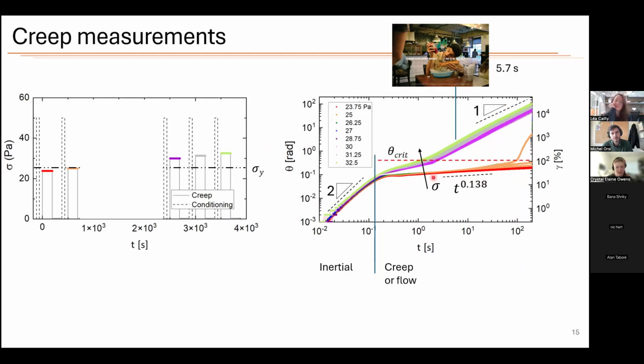And then we can see there also seems to be a little bit of a transition region here, so we can mark a critical rotation angle. Right, so this is tracking what is the angle of rotation as you apply the constant stress. And this is a function of time. So we have the angle here, and then we have the strain here. I mark both of those because the angle is something that we know for certain. We know where the vane is, we know how much it has rotated, but the strain is a little bit dependent on how much of the material has yielded. It's slightly less of a precise value, so I just mark both of those.